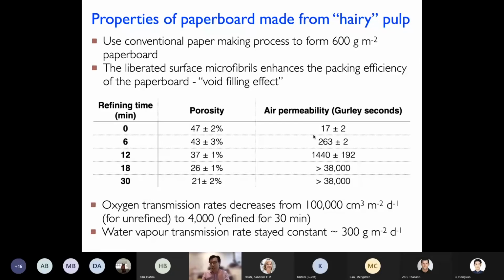So in this case, for air permeability, you should regard this as the higher the number, the longer it takes for air to pass through. So our oxygen transmission rate decreases down to 4,000 cubic centimeter per square meter per day. Our water vapor transmission rate stays the same. So that actually opened up some sort of possibility for us to use paper as some sort of packaging material for applications that require water vapor transmission, but not oxygen transmission. We're still exploring here at the moment.